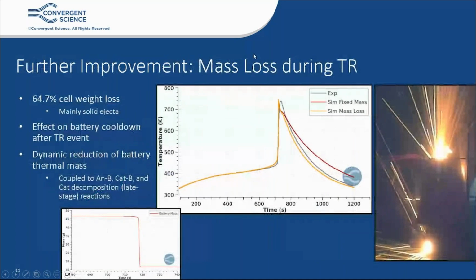Now, more recently, we have further improved our calibration approach and our simulation approach. Previously, our simulations were dealing with fixed battery mass, fixed battery density. So the curve in red, you can see that we weren't capturing the cool down trend after the thermal runaway event correctly. In reality, the battery in the experiment had a 65% mass loss. And most of the mass was lost during the thermal runaway event through solid ejecta. And this will have an effect on the subsequent battery cooldown because you have a different thermal mass.